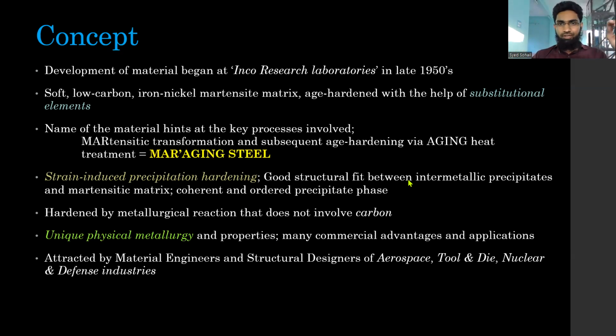But there is good structure between these intermetallic compounds which are formed in the aging heat treatment and the martensitic microstructure that is there already. So a good structural fit ensures that there is not much strain. It is strain, but not to the extent that it distorts the material upon heat treatment. So the distortion issues are also very less.